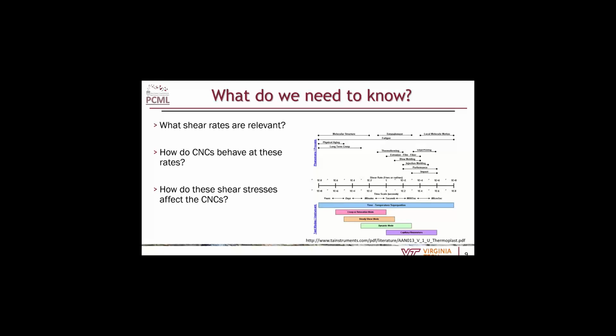That's sort of the max you can go, so there is a fair amount of data on cellulose nanocrystals at those rates and below. But what you'll notice is we're missing a large population of our processing performances, such as injection molding, blow molding, extrusion, and inkjet printing, which are all at rates higher than 100 reciprocal seconds. So if you want to know what those processes are going to do to our cellulose nanocrystals, we really need a way to look at those rates.